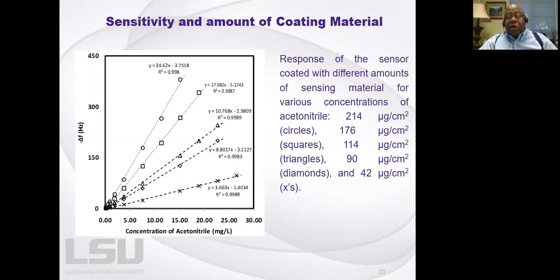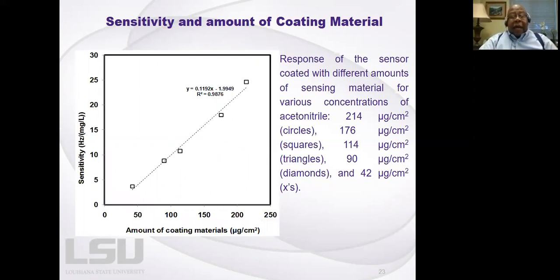And what he showed me was that different slopes would be exhibited for different gases. So I asked him to plot the sensitivity versus the amount of coated material. And as you would expect, there's a linear relationship between the sensitivity of the quartz crystal microbalance and the amount of coated material. Again, this is for various concentrations of acetonitrile as detected by that particular liquid.